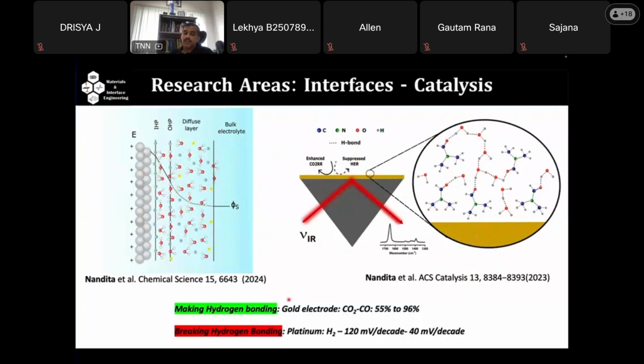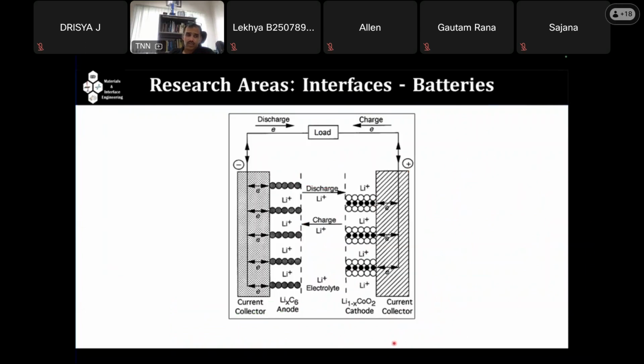So what I'm asking here is, by making and breaking of hydrogen bonds, you can actually control the reaction, the electron transfer reaction. I will show you several of these reactions, heterogeneous electron transfer reactions. Why is it called heterogeneous? Because the electron is transferring from an electrode, a metal electrode or solid, to a liquid. That is why it is called a heterogeneous electron transfer. In this heterogeneous electron transfer, thermodynamically, several reactions have similar energy. The free energies are similar, but by controlling the water structure, can you control the kinetics, and hence control the product? So either by controlling the thermodynamics or by controlling the kinetics, you can actually change the reactions. This is one thing we have shown.